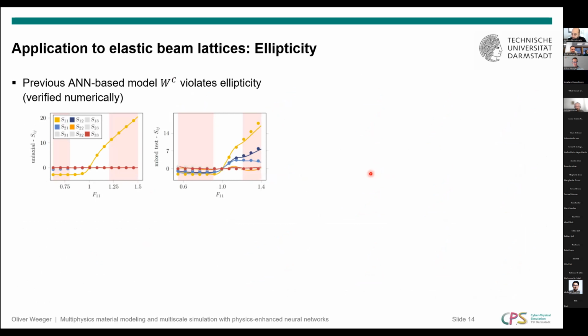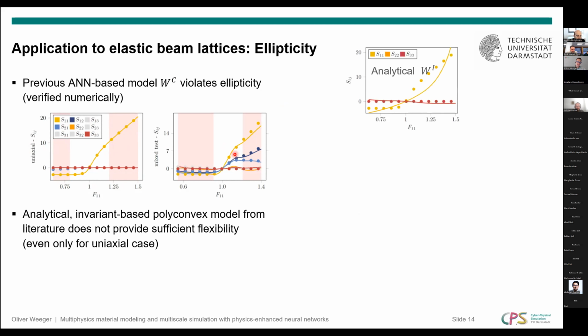However, now if we check the ellipticity condition, it's quite surprising to see, and this can only be done numerically, that we have a violation of this ellipticity condition, even here, for instance, in this uniaxial tension case, where the data and also the model looks very good. So what this violation of ellipticity means is that basically here you see the deformation component F11, and now the derivative of the stress with respect to other directions must be somehow weird, so that overall the second derivative is not positive definite at these points. And this happens here in this uniaxial case, but also in other cases where the range where the model is elliptic is actually quite limited. So this suggests that we might need this polyconvex model to obtain stable finite element simulations.